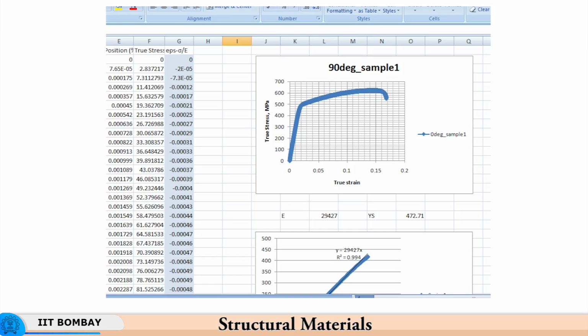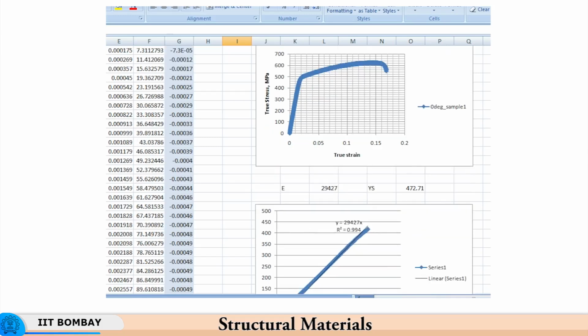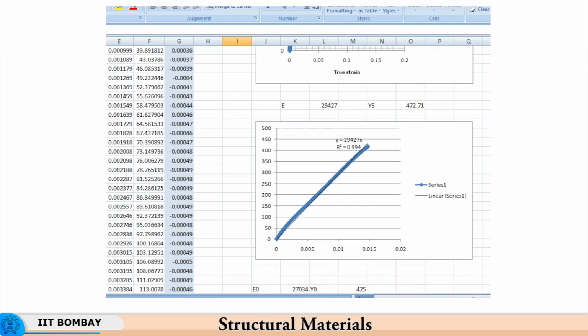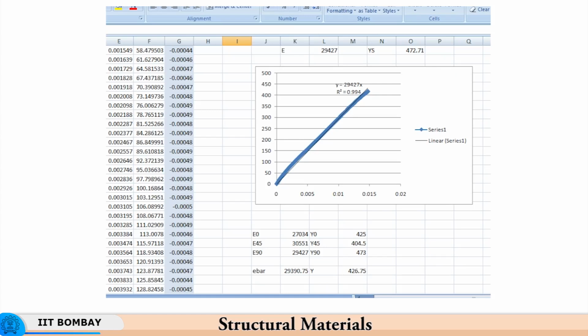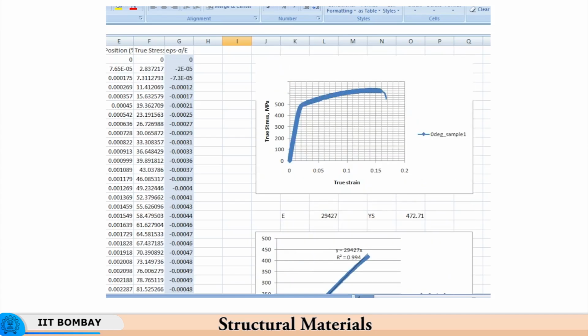So, you have engineering strain, engineering stress, true stress, and true strain. As the deformation increases, this coordinate increases, which means that the length of the sample is increasing, and so is the stress. If you look at this entire curve here, which is stress versus strain, you have this fairly linear region, and this is the point which can be seen as the yield point. Now, you can mark it by judgment or intuition, but how do you do it unequivocally, because different people might mark the point at different locations, and the scale is also very cramped, very compressed. So, there can be significant differences between the judgments of two individuals who want to identify the yield point.